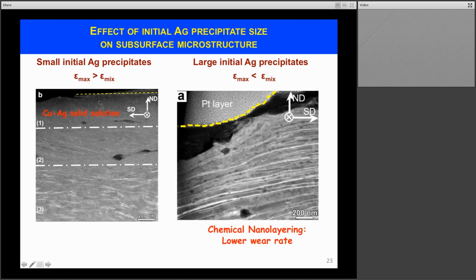However, when we started with a microstructure that is initially large precipitates, we see a totally different microstructure, and near the wear surface here, we observe the formation of nanolayers, alternating nanolayers of silver in bright and copper in dark. And you can see that these layers can become very thin, and this is the microstructure that has the best wear resistance.